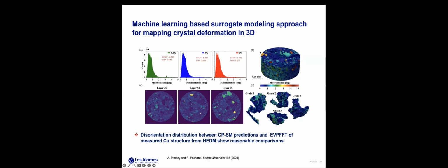The data was collected using HEDM, and you can see that again, I'm plotting the misorientation between the ground truth and the predictions, for different strain levels, and you can see reasonable accuracy of our surrogate model. And here's just a 2D spatially resolved misorientation plot extracted from these 3D volumes. And even though the Dream 3D produced synthetic data have equiaxed grains and random texture, the model was able to accurately predict reorientations even in the complex morphology of measured HEDM data.